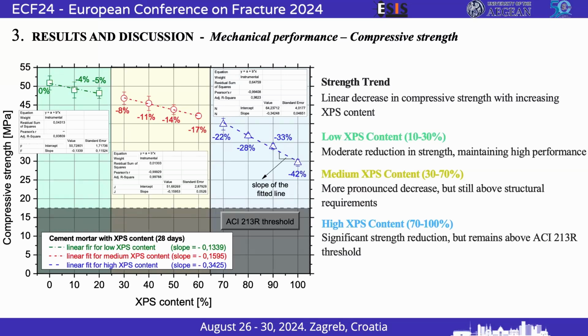With regards to the compressive strength, here you can see the different XPS content that substituted sand from 0%, which is the reference sample, up till 100%, which is total substitution of sand with the ground XPS waste.